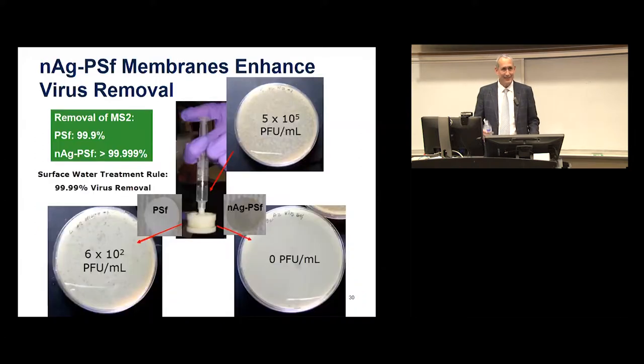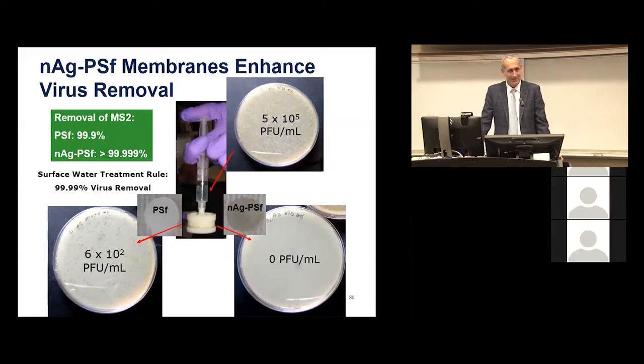A nice surprise was that these membranes have relatively large pores. So the phages that are a lot smaller can get through those pores, and as you can see here, they break through. But when the membrane is impregnated by silver nanoparticles and it releases silver ions into the pores, these pores have a potent antiviral activity as well, and no viruses are breaking through, so that was a nice surprise. So this is about preventing biofilm formation.